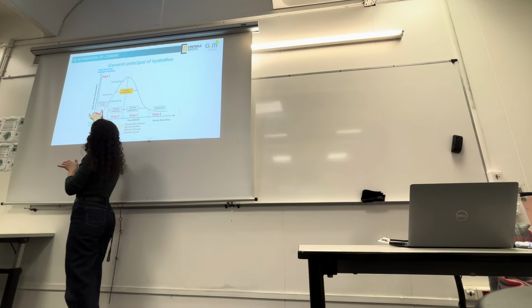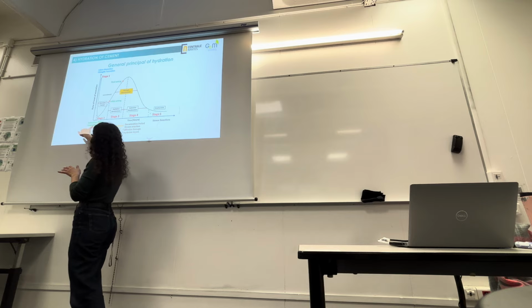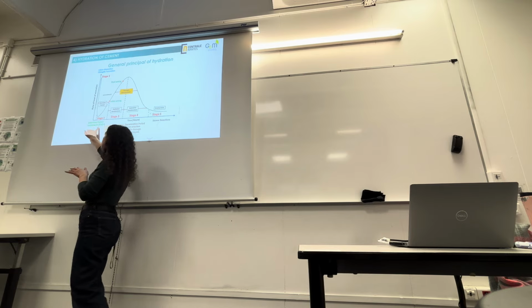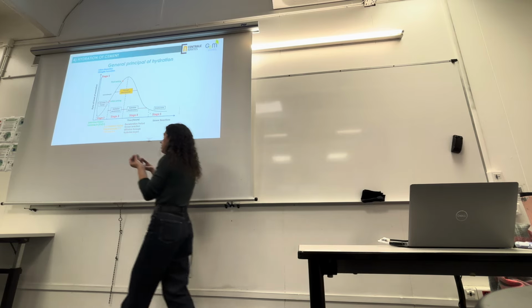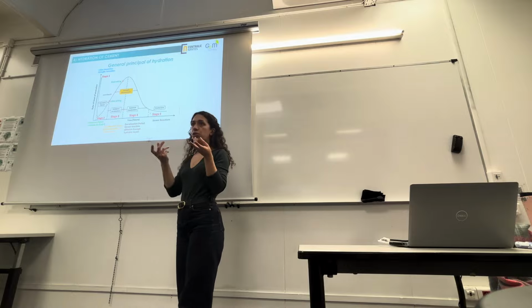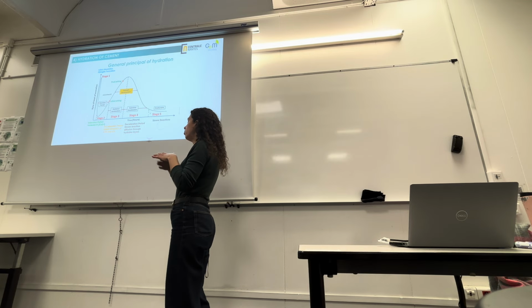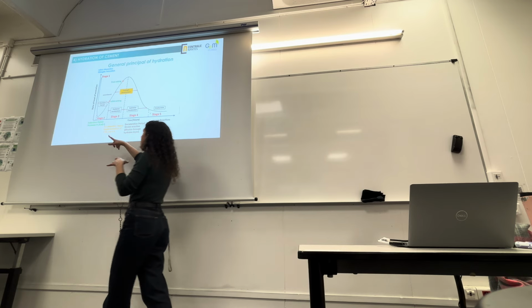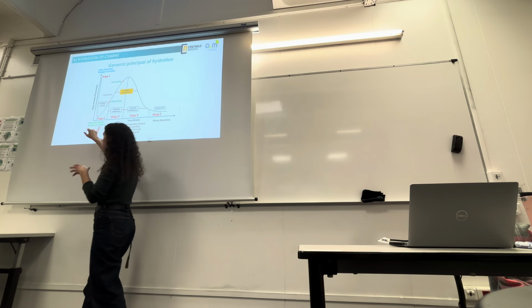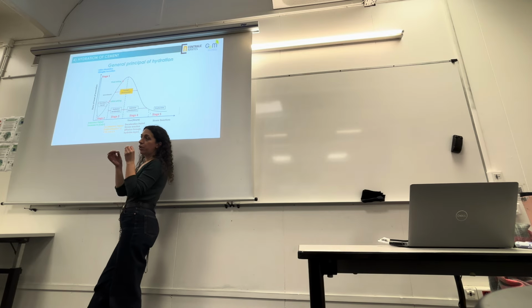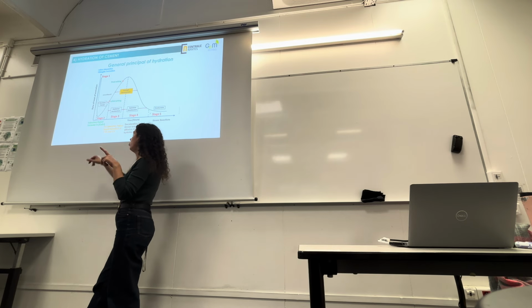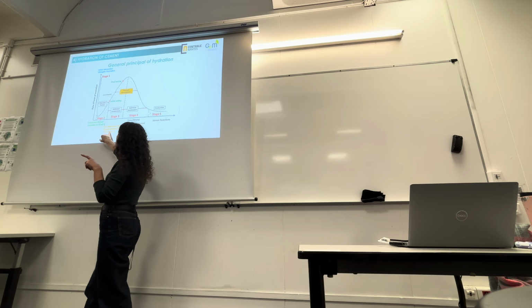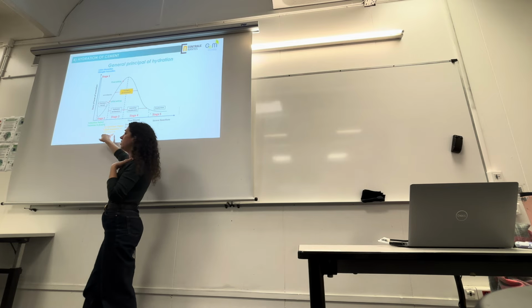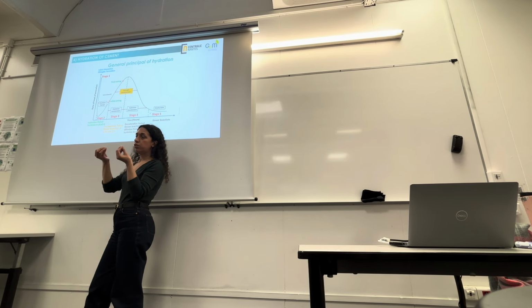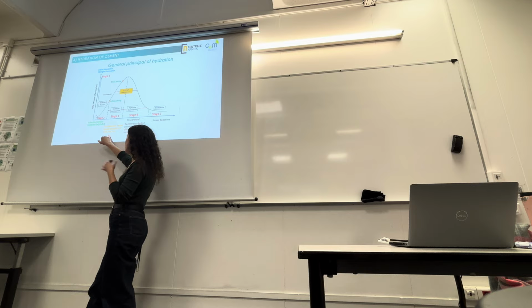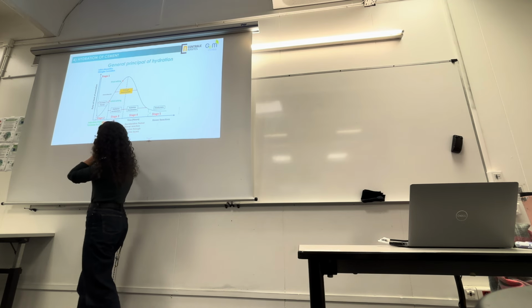Then we enter the dormant period, stage 2, induction period, increase in calcium inside the solution. The calcium ions concentration will increase, and then once you reach a certain point of calcium inside the solution, you have rapid formation of CSH and CH. They can precipitate. There is enough calcium for the precipitation of CSH and CH. This happens during stage 3.